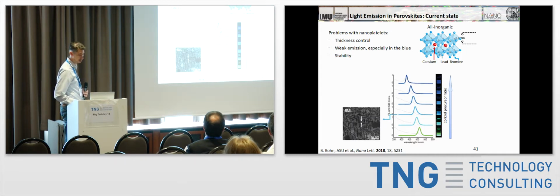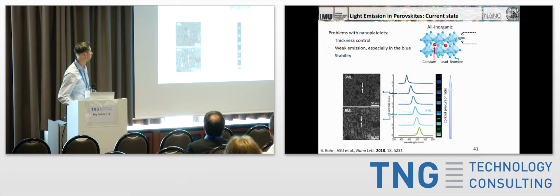And as you can see here, again, we were able to do this fine tuning of the colors, but you can see the spectra are only single peaks there and actually quite narrow in this case. And if you look at electron microscopy images of the nanocrystals in here, you can see these are all nanoplatelets with a single thickness of 5 monolayers. In this case here, you can see they're slightly thinner. These all have 3 monolayers.